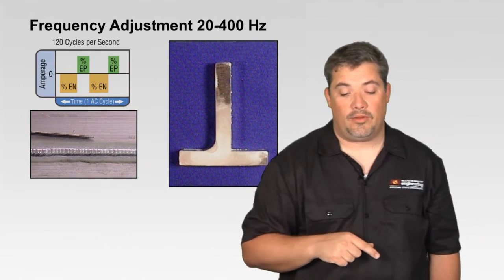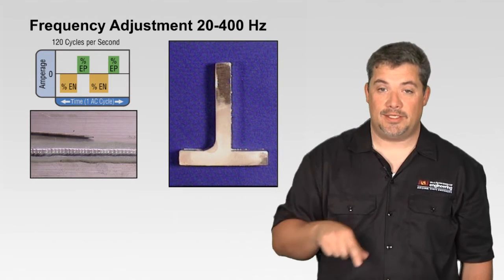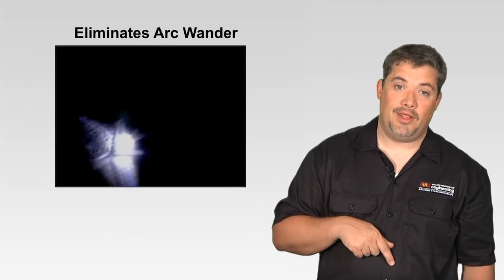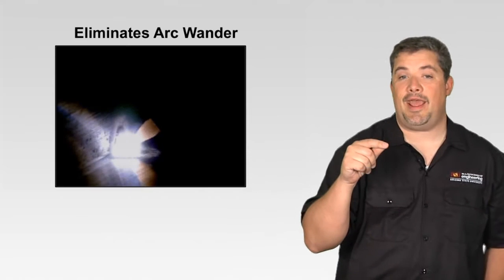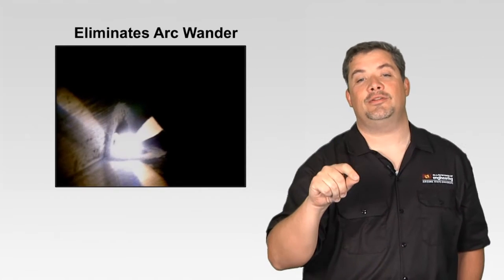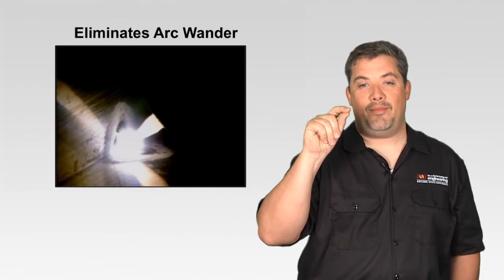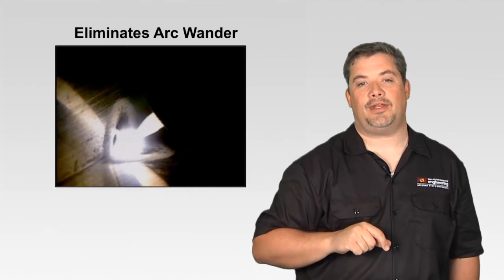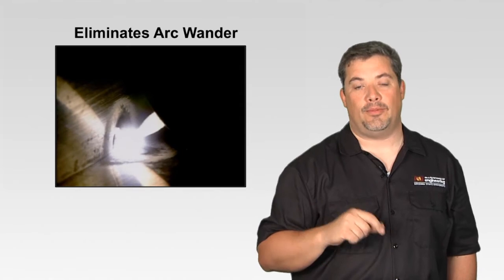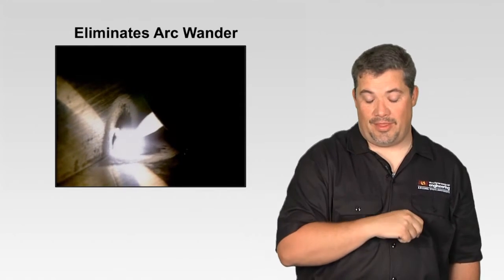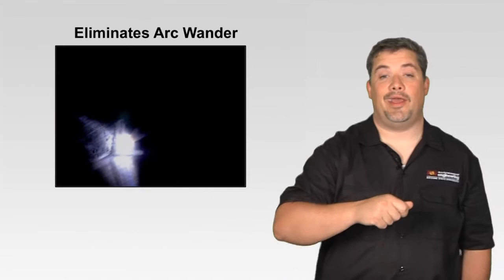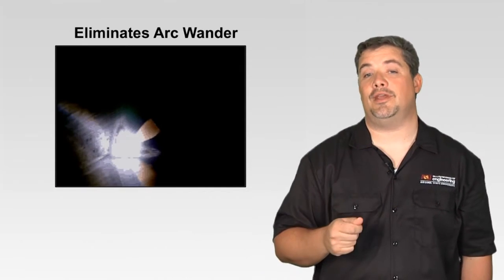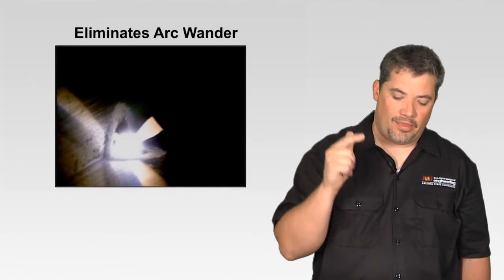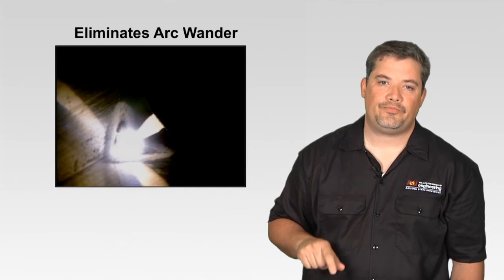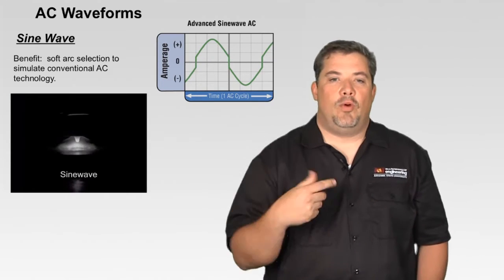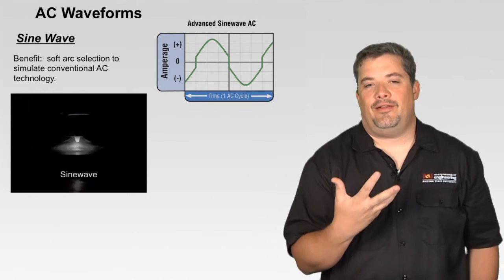So when I go to my higher frequency adjustment, you can see it's a lot easier to break down that corner, and this video is the best illustration. You can see now I have that sharp tungsten, I have a high hertz, I have more electrode negative, and I'm able to really focus that arc energy and direct it exactly where I need it to go, as opposed to the conventional way. This right here is probably the best illustration to see why you want to have an advanced TIG machine versus a conventional TIG machine. Because if you're doing aluminum, this is huge, very important stuff. So these waveforms also affect this to another scale on a smaller scale.